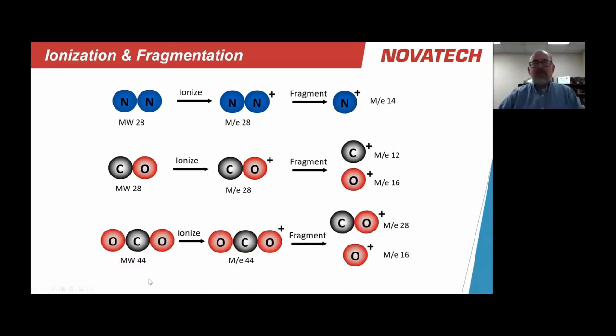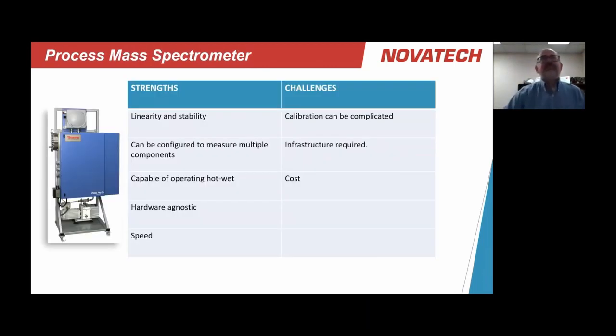And then if I throw one more in, for example, carbon dioxide, I see that I get another peak at 28. So what this means is that, yes, it's a tremendously powerful technology, but it means that calibration can become interesting. We have to calibrate not only for the components we want to measure, but we also have to calibrate for the components that may also be present in the sample. So it can be more complex from a calibration perspective as compared, for example, to a GC, where we really only look at the components we want to measure.